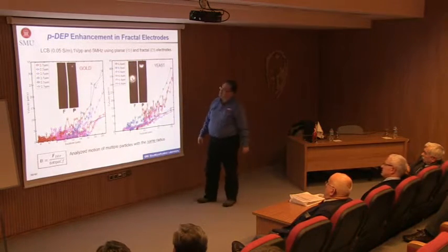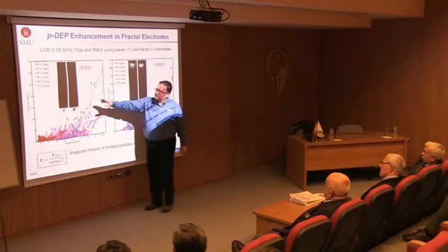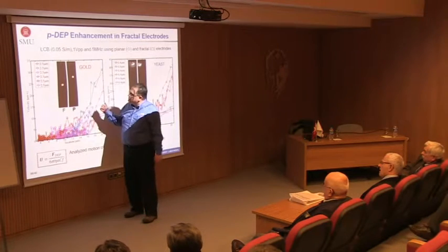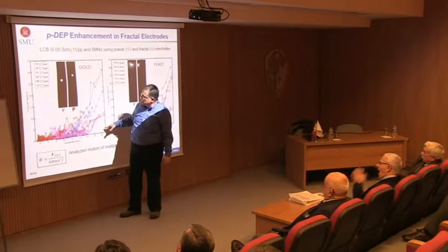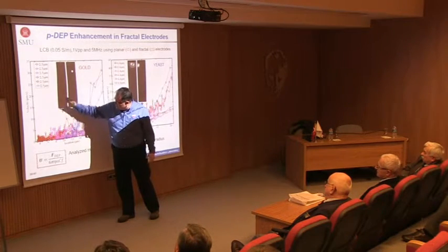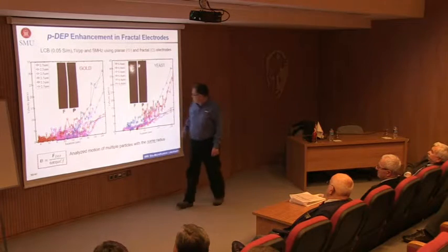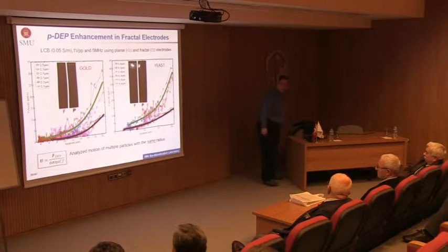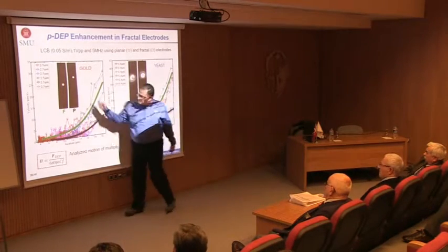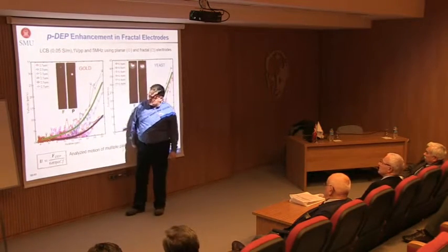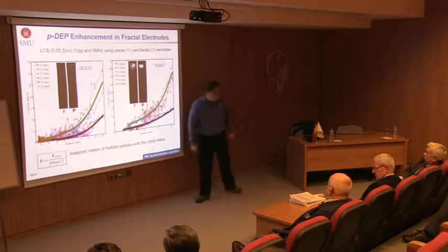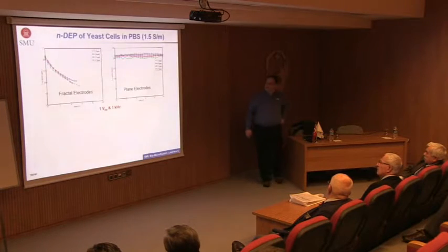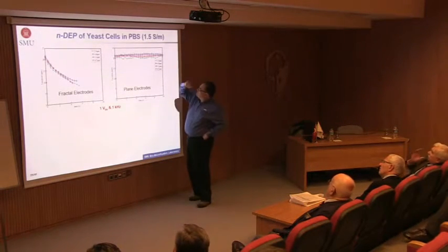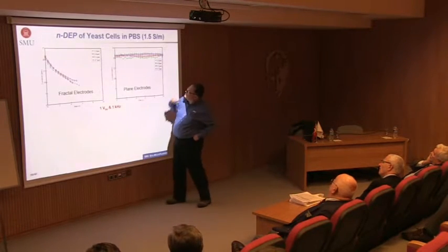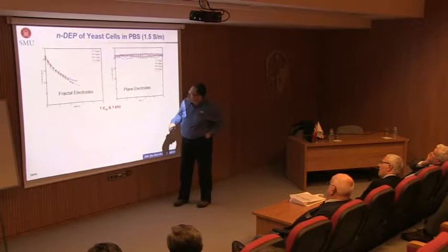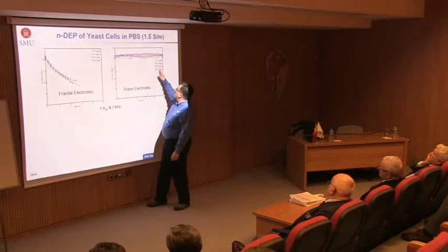So we looked at identical diameter yeast cells and gold nanoparticles. And because we're showing velocity versus location, I had to take the derivative of the data, and there's some Brownian motion. That's why I have a lot of noise in this. But there are two general trends. Basically, the particles subjected to fractal electrodes move faster than with the plane electrodes for both cases. And we have indeed shown that similar things happen, even at 1.5 Siemens per meter, where I regularly would not see any DEP response.